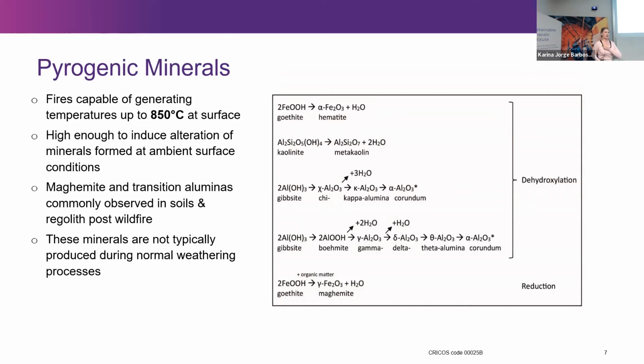Just want to touch a little bit on some of the pyrogenic mineral assemblages that we happen to see following a fire. So as I mentioned, fires generate temperatures up to 850 degrees, and this is well and truly high enough to start causing mineral phase transformations in the soil. And what we see is things like goethite, so that's quite a low temperature iron hydroxide, dehydroxylates forming hematite. Kaolinite is a very ubiquitous clay mineral, and we form a mineral called metakaolin. If there's gibbsite present, it can form a number of these sort of nerdy looking formulas, and I won't get into detail about them. If you want to ask me and you're interested in mineralogy, it's super cool, but I don't want to put you to sleep. But we call these the transition aluminas, and essentially they culminate in corundum at about 1200 degrees.